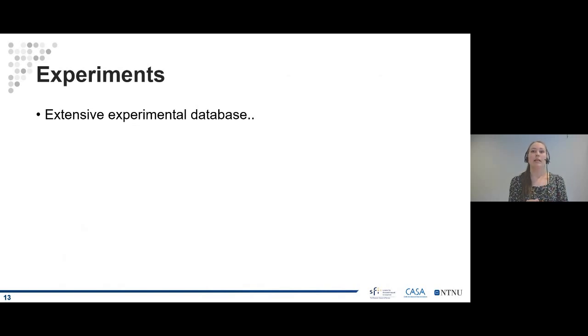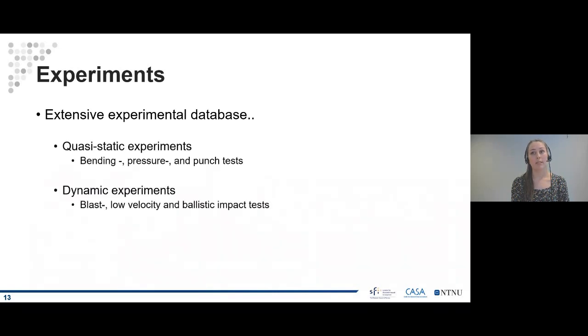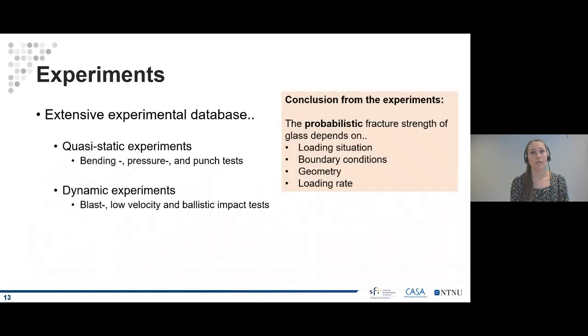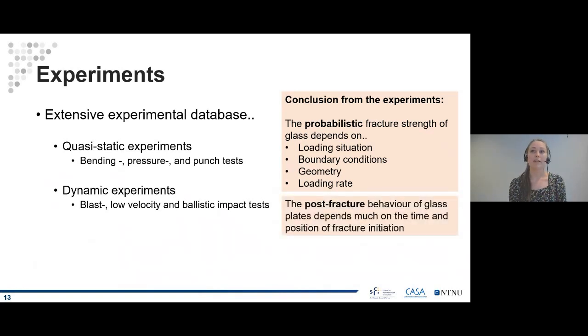During my PhD, we performed a lot of different experiments. We performed quasi-static and dynamic tests, including bending, pressure, impact, and ballistic impact tests. We got two main conclusions from these experiments. First, the probabilistic fracture strength of glass depends on the loading situation, the boundary conditions, the geometry, and the loading rate. Also, the post-fracture behavior of glass depends on the time and position of fracture initiation.